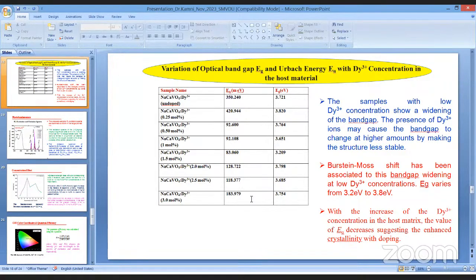The samples with low dysprosium concentration show a widening of the band gap as we go from 3.7 to 3.8. The presence of dopant ions may cause the band gap to change at higher amounts by making the structure less stable. A Burstein-Moss shift has been associated with this band gap widening at low dysprosium 3+ concentrations, and you can see that the band gap basically varies from 3.2 to 3.8 electron volt. With the increase of the dysprosium 3+ concentration in the host matrix, the value of Urbach energy, which is basically the amount of disorder in the material, decreases, suggesting enhanced crystallinity with the doping concentration.